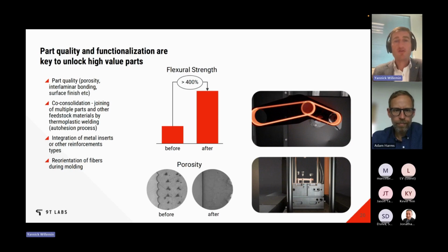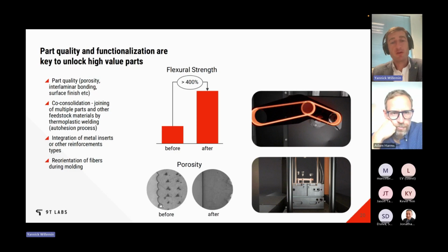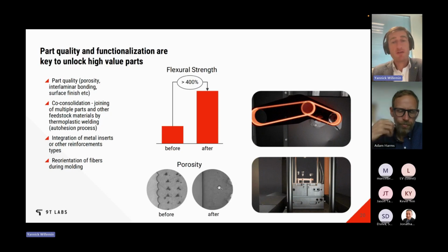So long story short, what do we do in the fusion process? You see at the bottom, in the middle, how the structure looks before. So after printing, you still see quite some porosity. It comes from the material itself. Tapes are porous to a certain point. It comes from the deposition, obviously. And you also see at the surface, it's not flat, meaning you will also see with your eyes some layers, meaning the interlaminar strength is far from perfect. What we want is what is on the right, and that's how it looks after the consolidation phase.